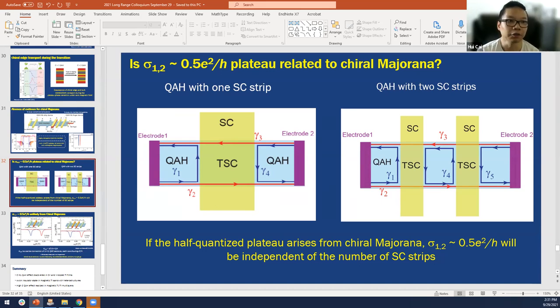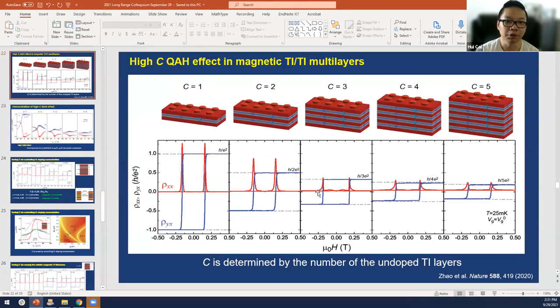Hi, this is Hui. I have a question about the multi-layer structure that you've built to realize the high Chern number quantum anomalous Hall effect. So here what you need is a layer of normal insulator and a layer of magnetic topological insulator. Actually, bismuth antimony telluride or this group of materials can be a normal insulator below a certain number of quintuple layers. So why don't you just use a thinner layer of this bismuth telluride as the normal insulator layer, and then a not so heavily doped magnetic layer as the magnetic TI layer?